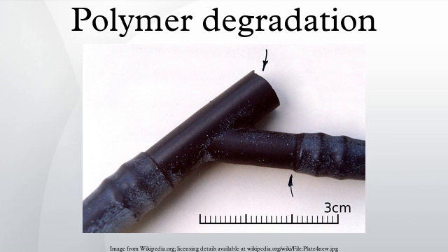Oxidation is usually relatively easy to detect owing to the strong absorption by the carbonyl group in the spectrum of polyolefins. Polypropylene has a relatively simple spectrum with few peaks at the carbonyl position. Oxidation tends to start at tertiary carbon atoms because the free radicals formed here are more stable and longer lasting, making them more susceptible to attack by oxygen. The carbonyl group can be further oxidized to break the chain.